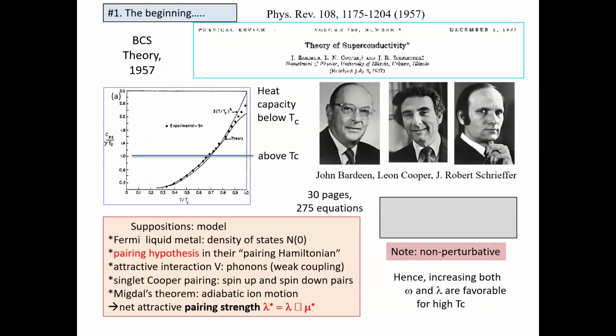Okay, get to the main development in the theory, and that was due to Bardeen, Cooper, and Schrieffer in 1957 in a paper of 30 pages and 275 numbered equations. And as a graduate student, I went through in detail at least the first 30 pages here and filled in the missing parts between the equations that they provided, and convinced myself that they didn't make any algebra mistakes anyway. And what they found was that with their theory, they could extract an equation which would give the superconducting transition temperature in terms of a characteristic vibrational frequency of the ions and an effective pairing between the electrons, which needs to be attractive.